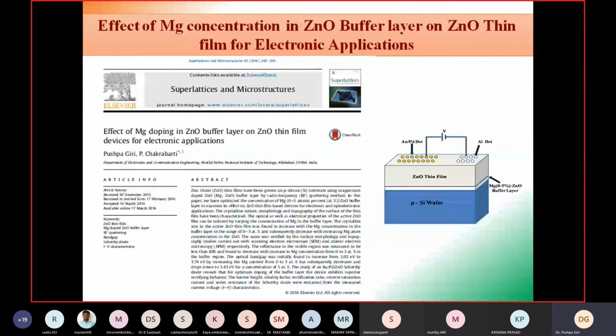And by incorporating the doping, compared with when it was done without doping, and then 1%, 2%, 3%, 4%, 5%. What we have seen at 3% of this magnesium doped zinc oxide buffer layer, this is the final, the upper layer. This shows a very nice and smooth curve, and before and after that we are not getting much. 2% is also acceptable, but at 3% we are getting the best result.